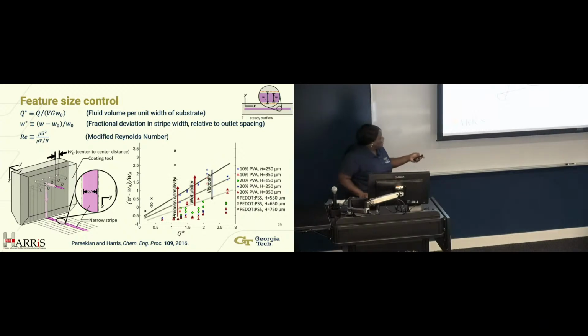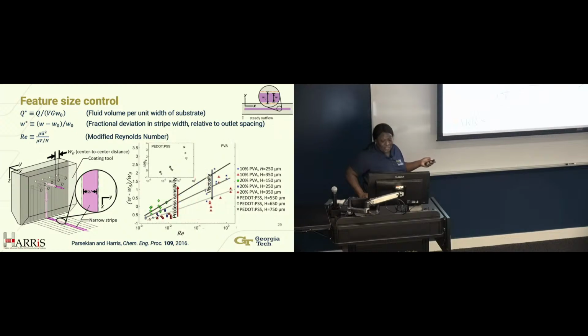And so the process sensitivity is high. The wettability is high as the viscosity goes down. And if we look at it from the Reynolds number, so thinking about process speed, then it becomes even more interesting because we don't have as much scatter. All of a sudden, things begin to collapse in these lovely groupings, and you can see that there's little to no change relative to the material property groups, subgroups.